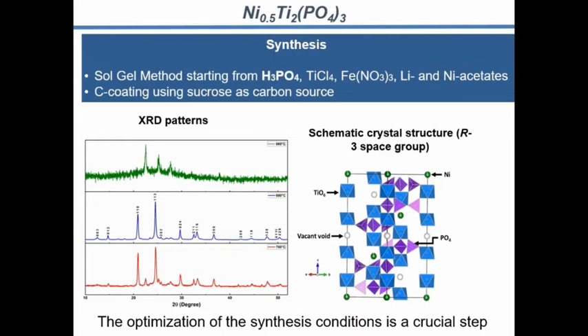So this nickel titanium phosphate was prepared using the sol-gel method, starting from phosphoric acid and some titanium and nickel salt. The product was prepared first, and then we use a carbon coating process using sucrose as carbon source. In fact, we mixed our phosphate with sucrose and put it in the furnace at 400 or 500 degrees, but under inert atmosphere. And depending on the temperature of synthesis, you can see